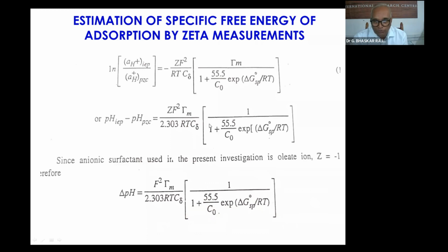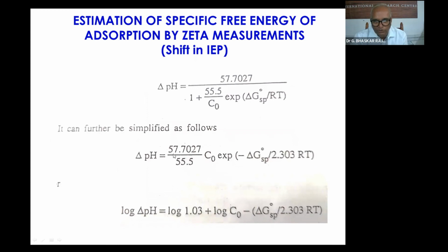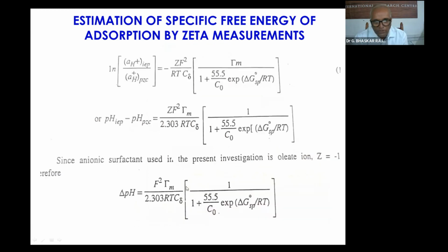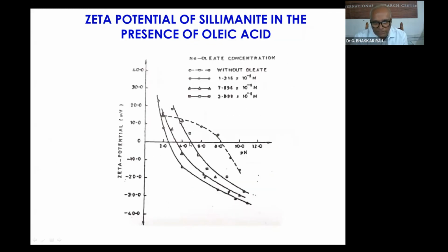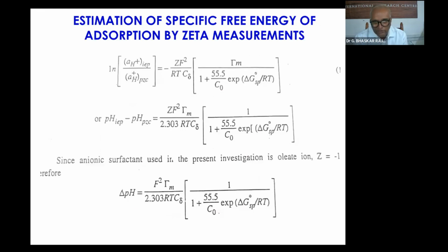Dr. Pradeep and others have developed equations like this, where you can find out the final value. It's a delta pH, that is, the shift in this pH. You will know it experimentally, because this shift in pH can be noted. And Z is the valency of the reagent which we have used.